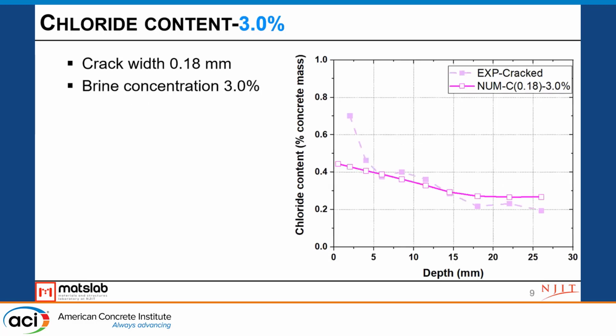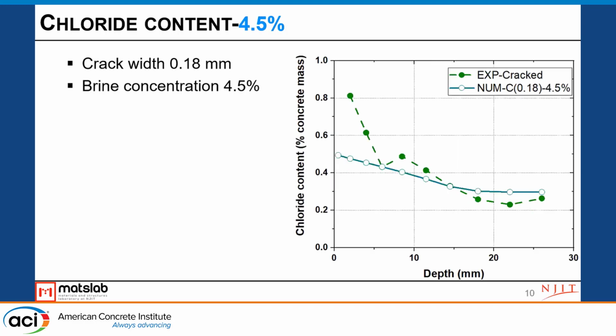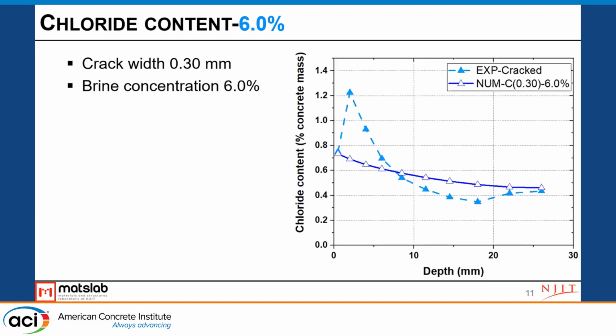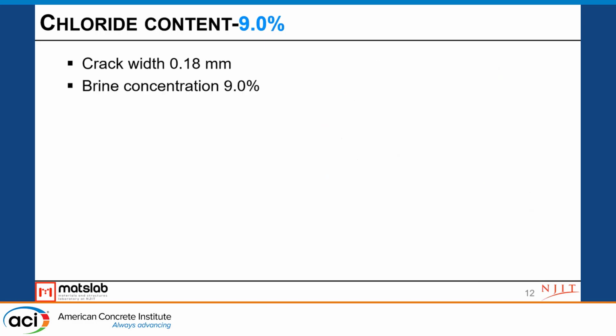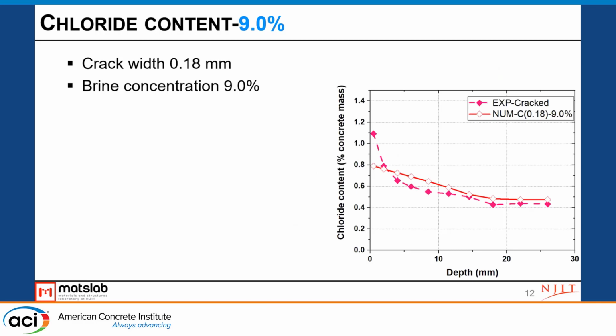So on and so forth, we got a similar trend with the 3% surface chloride ponding condition, and also for 4.5 and 6% ones. Here we used a different crack width because we want to compare the result directly to what we get from the test. And same with the 9% one. So we got a series of these tests and numerical simulation results.